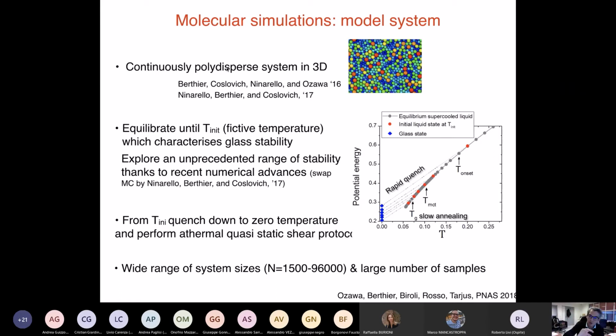Instead, if you follow the equilibrium line, you arrive, let's say, at TG, and then you do the quench at 0 temperature, then you construct a system which is very well annealed, and that we think has a low degree of disorder. And this is really the breakthrough that allows us to study this theoretical idea that I discussed before for the yielding transition. The system sizes used have been quite huge, from 1,500 particles to almost 100,000 particles, and then a very large number of samples.